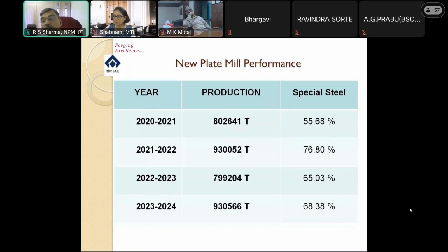The major contributor to this was boiler quality grades, and most of them were taken by mega infrastructures. So that was the major reason why we achieved 76. After that, in the following 2 years, we have not achieved that figure because orders are not there from mega to that extent in boiler grade. And in 22-23, again there was a dip in production because of a series of major breakdowns. 2-3 breakdowns were there that limited our production. But immediately after that, in 23-24, we bounced back and again crossed our APP and the best figures till now, 9,30,566, and special steel was 68%.